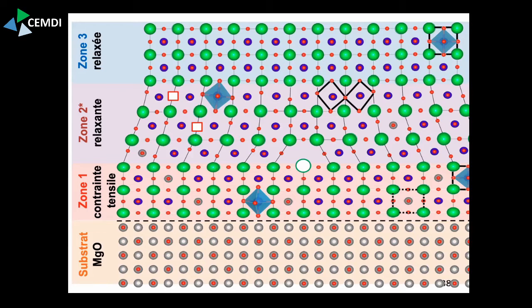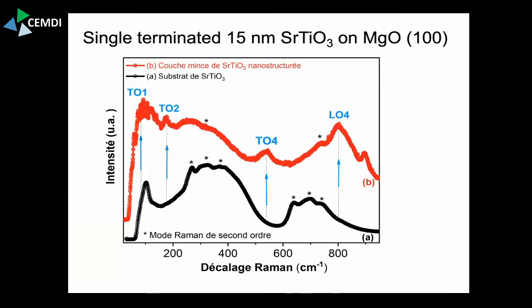So this is a zone where relaxation starts. And at some point, this relaxation is over, and you get all these gradients in here. And at some point, you continue just growing your bulk material as if there has never been an interface because it's fully relaxed. So if we look at such a film, we should expect that it should look different from the bulk. And indeed, that's what it is.